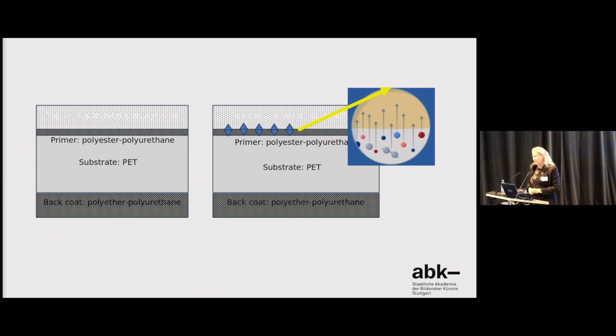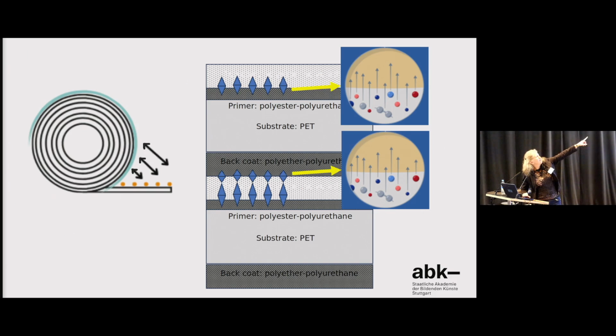But if you store your tape under high humidity, under elevated temperatures, and with high pressure on a tight pack, because you are in a radio archive, and the last thing the operator did before putting the tape into the archive was high-speed rewinding and get rid of it and put on the next one. Then you have such a high pressure, then you have all the thermodynamic factors which open the pores, let water come into the material, and the pressure gets higher and higher. And then it happens that the primer migrates through the coat to the next back coating, where you also have polyester polyurethane. And then they bind together, and delamination takes place.